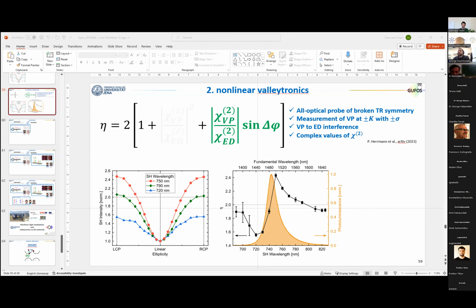However, this is not exactly the case, because the exact shape will depend on the quality of the material and on the substrate. And this comes directly from the Kramers-Kronig relations. This is something that we did not calculate. We have this material, we have the photoluminescence, we did not go into details up to the Kramers-Kronig relation. The other thing that I should mention is that this shape depends on the interference between the valley polarization and the intrinsic response. So while for the intrinsic response, we can look at the absorption and somehow estimate what we would expect, for the time reversal symmetry, we don't have any benchmark.